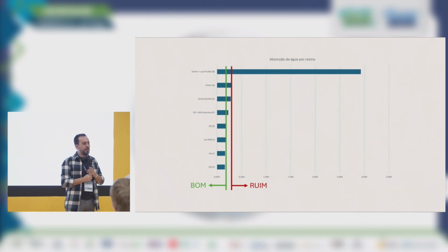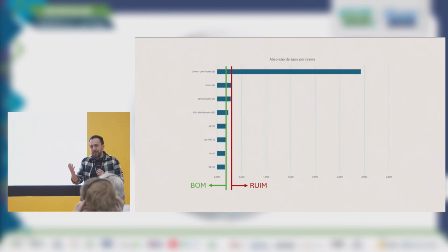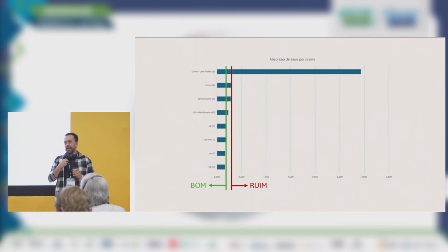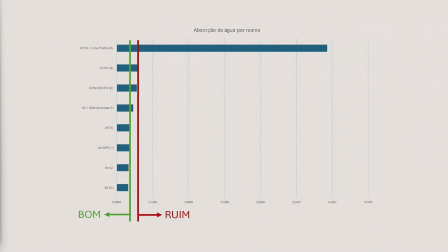And now, the main disappointment for me was, and I wish the result had been different, above all, SMC people who use a low profile additive, which we know has a wonderful finish on the parts. It's water soluble, therefore it would not be osmosis resistant. But I wanted to test how much worse that additive would be. Much, much worse. In fact, I took it off the graph essentially. It's off the chart.